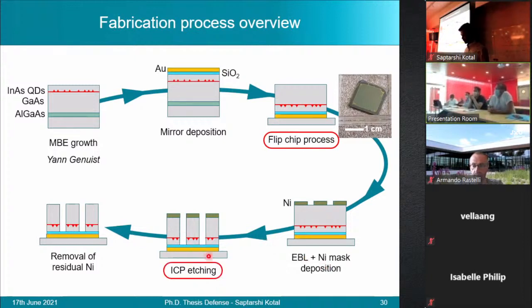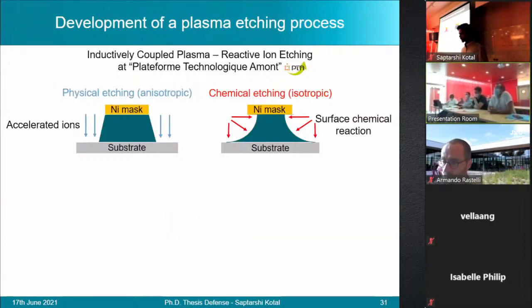During my work, I also developed a new inductively coupled plasma etching recipe. The etching process consists of three broad processes that happen simultaneously. We have the physical etching process, which is anisotropic in nature and consists of the bombardment with accelerated ions on the substrate, thereby physically etching them.